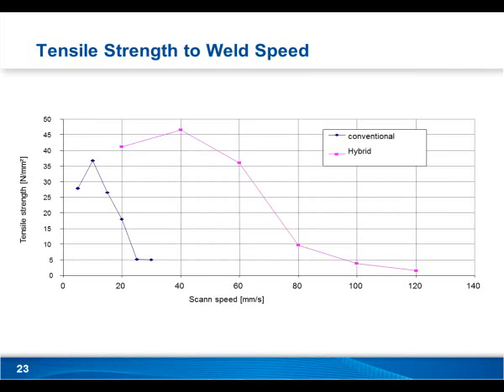Here's an example of tensile strength to weld speed. As you can see, we have conventional contour welding over here, and then the pink line is hybrid welding. If you speed up your scan speed with contour welding, you can see a very quick drop in tensile strength, whereas it tends to even out and stays very high with hybrid welding. Also, I want to note that this was done at very low laser powers, so we can actually turn up the laser power and achieve higher weld speeds.